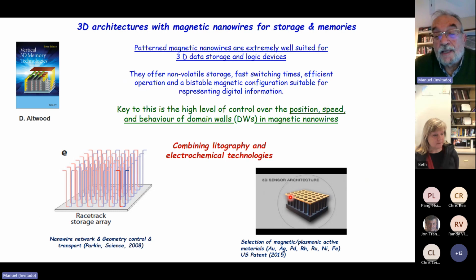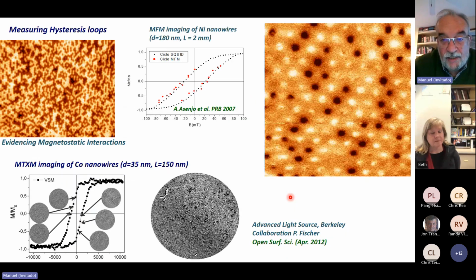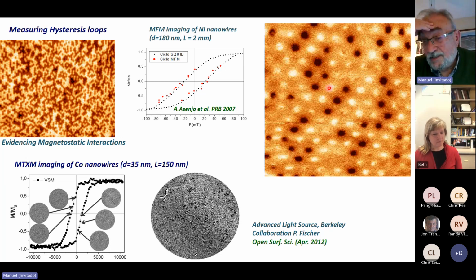Well, in our case, once we have prepared the arrays of nanowires, we characterize the array first. This is the hysteresis loop of an array of nickel nanowires, the black points. And here to the right, we have a magnetic force microscopy image of an array where you see black and white points. Individually, each black or white point corresponds to one individual nanowire. This indicates that in some of them the magnetization is pointing up, and in others the magnetization is pointing down.